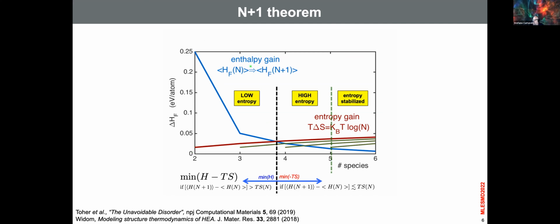There is a region of low entropy where everything is dictated by enthalpy. So here, let's say from 2 to 4 species, this is where you would find the most stable configuration. You would really have to minimize the enthalpy. This is what we have been doing for 30 years.